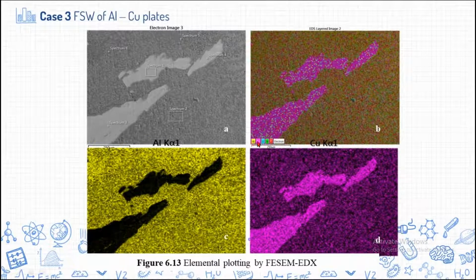So we unhighlighted all the things and only selected the aluminum element. This yellow portion is completely aluminum, whereas the black portion we don't know what it is. Then in the next step, we unhighlighted the aluminum and only highlighted the copper, which is the pink color. So we observed copper is there over here. Leaving aside these portions, if you observe outside of this one, both aluminum and copper are homogeneously mixed throughout the entire weld zone.